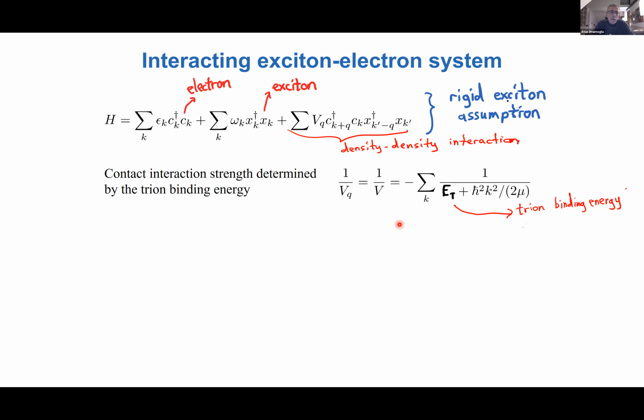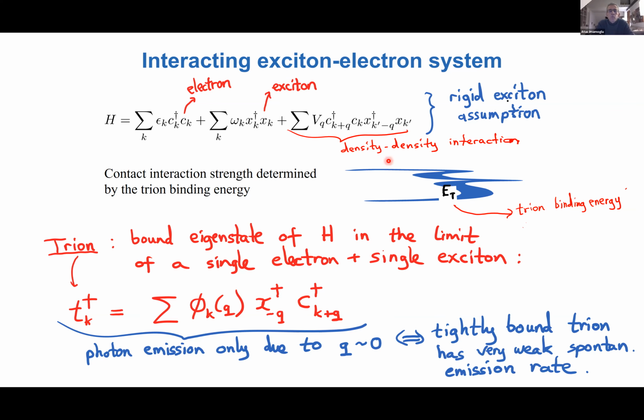Now, if we really have only one electron and one exciton, then we can diagonalize this Hamiltonian using a variational approach. And we will find that there's a single bound state, and this is the trion state. The creation operator for a trion, one can write in terms of the product of exciton and electron operators with the wave function that is relatively tightly bound. So basically, the size of the trion is about 2 nanometers, so not so different than that of the exciton.